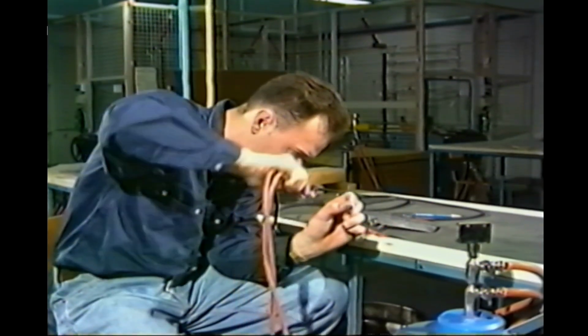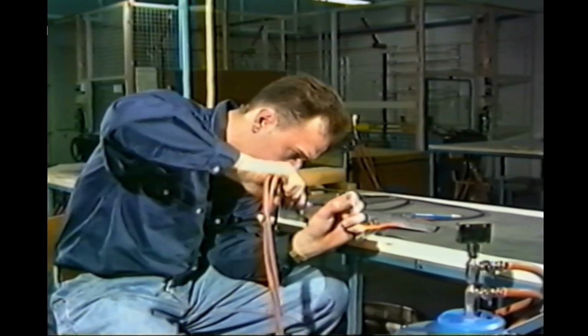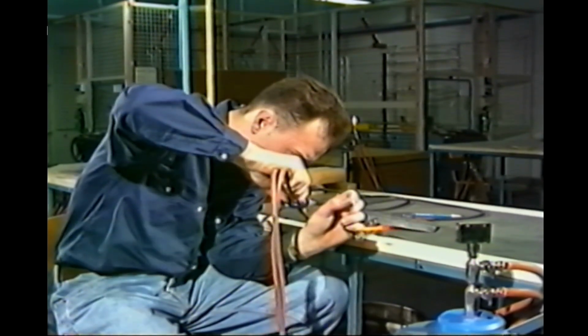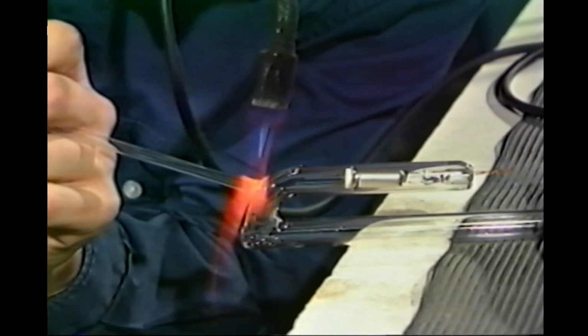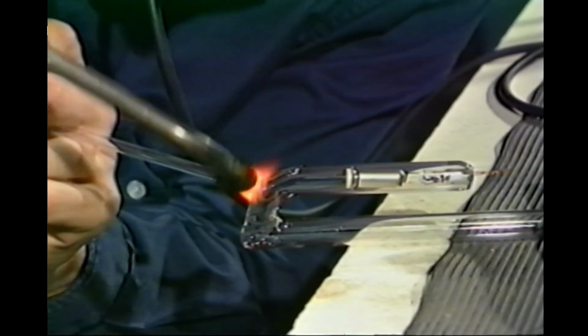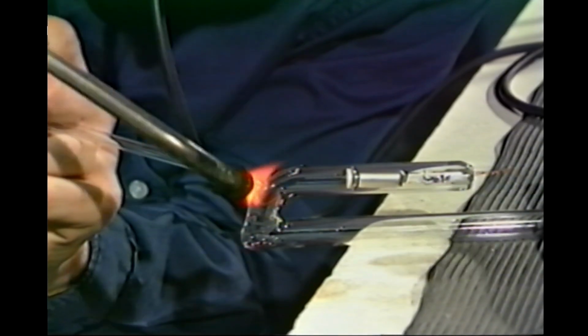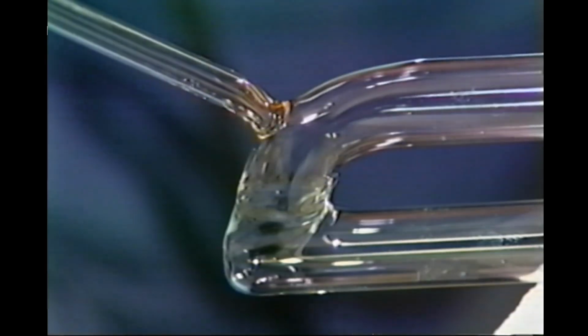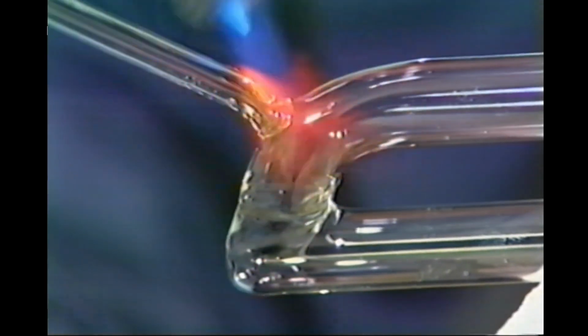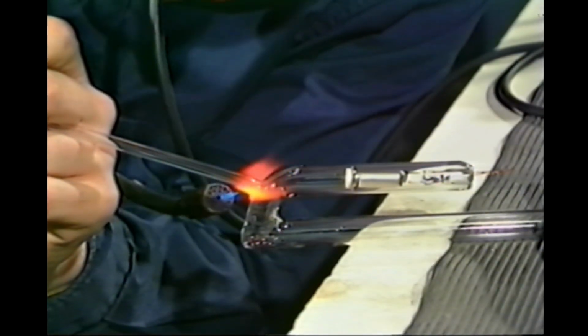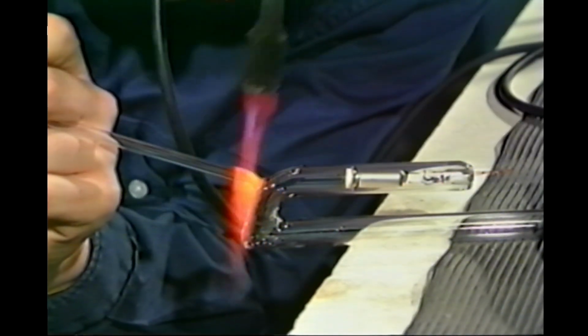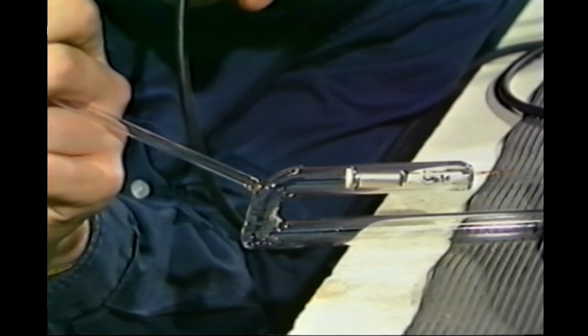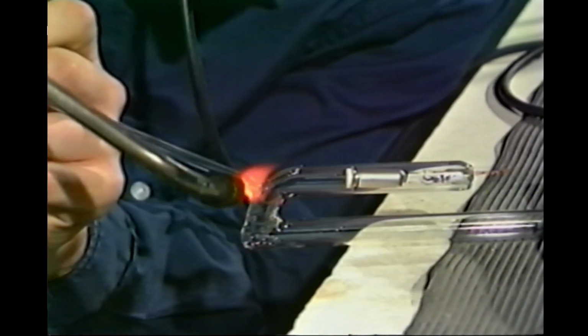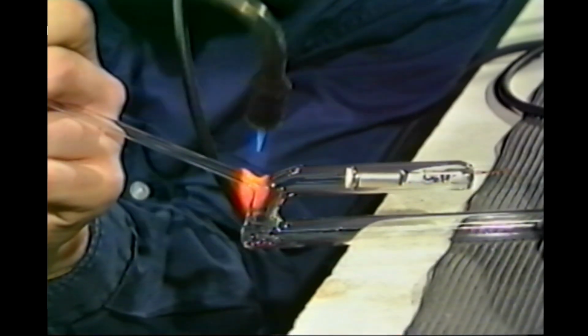Again, keep the angle of the flame correct and complete full rotation with the flame to produce some heat right around the joint area. When the glass is red hot and has reduced in diameter, remove the flame and blow gently to restore the correct diameter, making sure not to pull the stem out with the support hand. Repeat this method until a good, clean, clear, ridge-free joint is achieved.